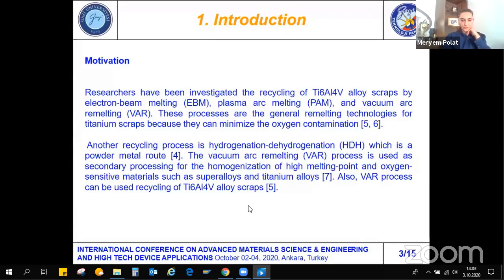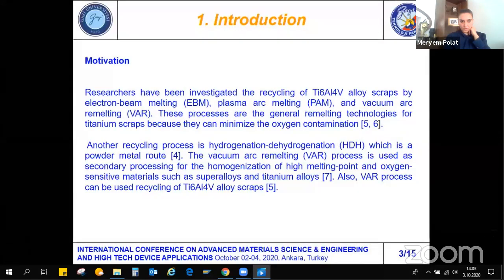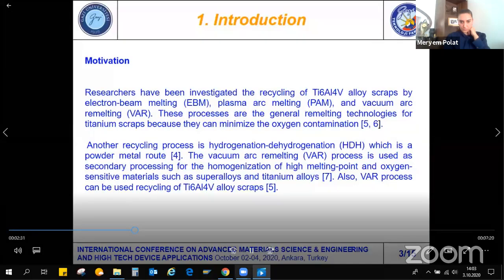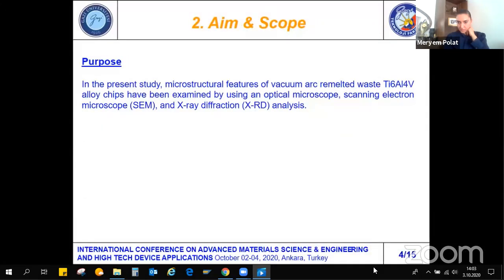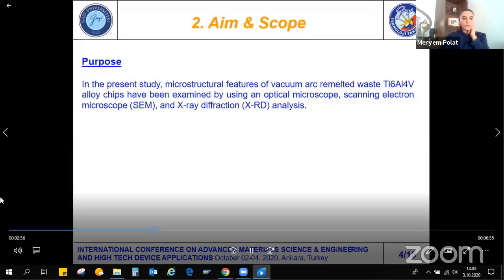The vacuum arc remelting process is used as a secondary processing for the homogenization of high melting point and oxygen sensitive materials such as superalloys and titanium alloys. Also, the vacuum arc remelting process can be used for recycling of titanium 6 aluminum 4 vanadium alloy scraps. In the present study, microstructural features of vacuum arc remelted waste titanium 6 aluminum 4 vanadium alloy chips have been examined by using an optical microscope, scanning electron microscope, and X-ray diffraction analysis.